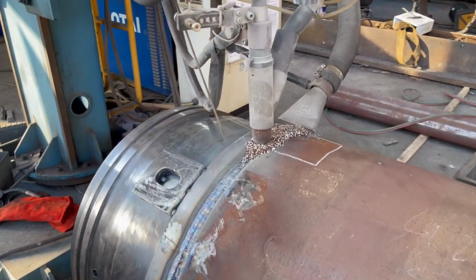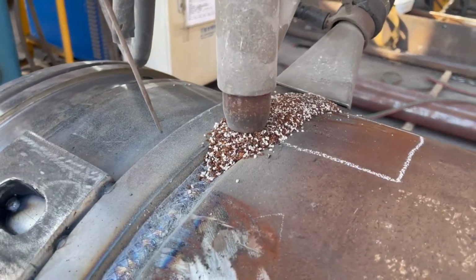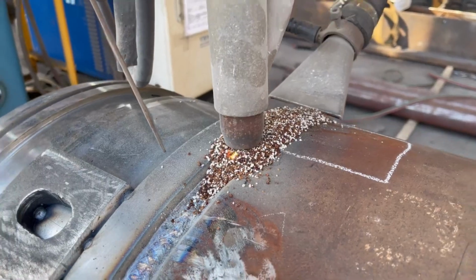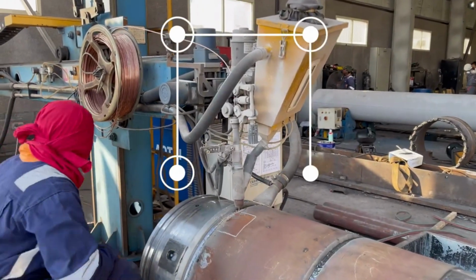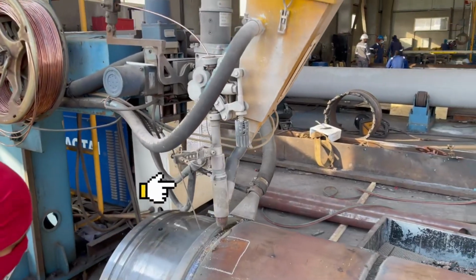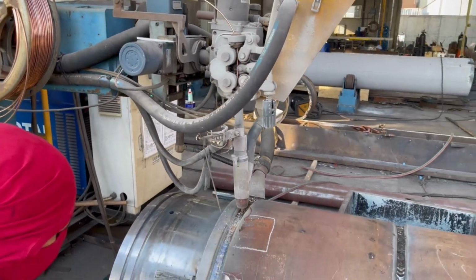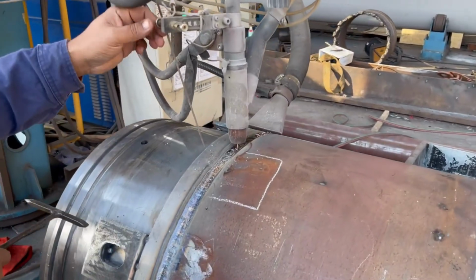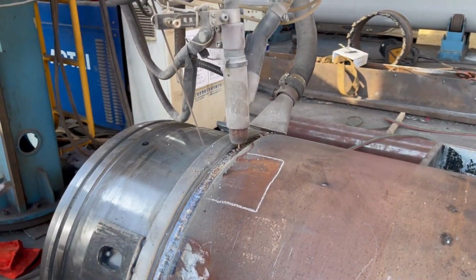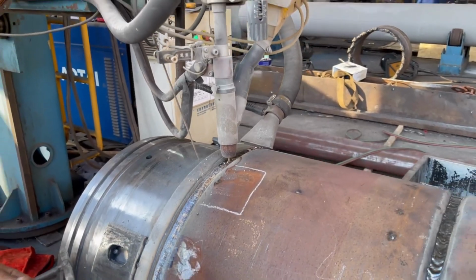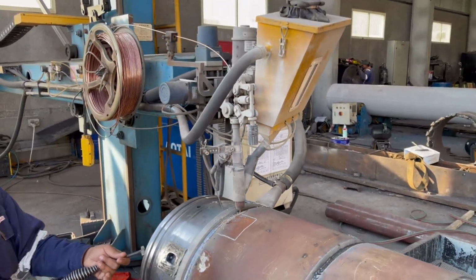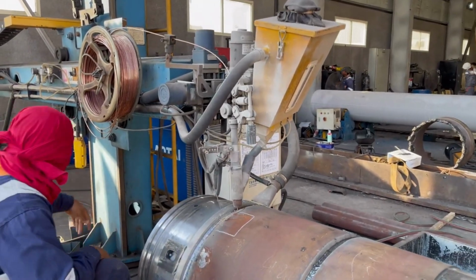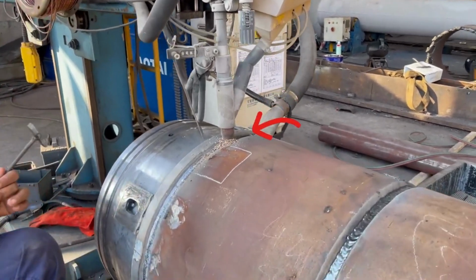Why does SAW produce such high deposition rates? One of the biggest advantages of submerged arc welding is its incredible productivity. But why is it so fast? Several factors contribute. First, the continuously fed wire eliminates frequent stops. Second, the flux blanket allows higher welding currents without excessive spatter. Third, automated systems maintain consistent travel speeds. Together, these factors allow SAW to deposit far more weld metal per hour than many conventional welding methods. This is why large manufacturing facilities often rely on SAW when productivity is critical.